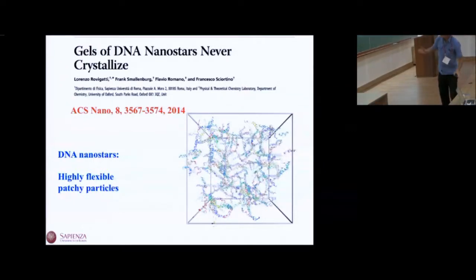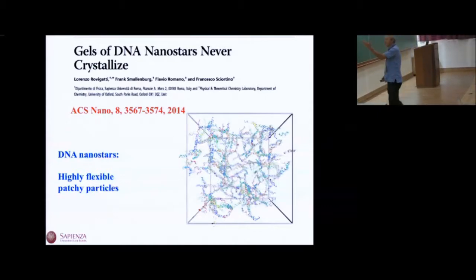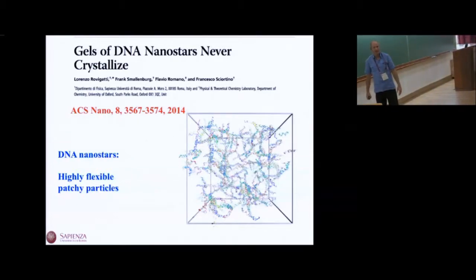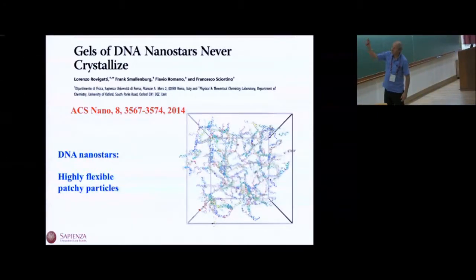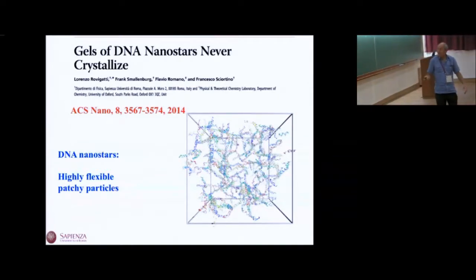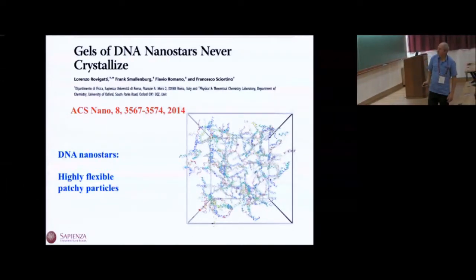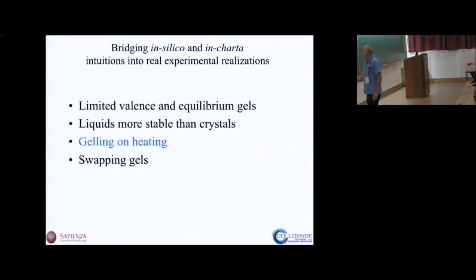It does not crystallize ever. On the computer, you can calculate the free energy with this Frenkel-Ladd type of methods for the DNA gel, or you can do it for the DNA crystal, and you can show that the free energy of this very flexible particles is really lower than the free energy of the crystal. So the gel is the thermodynamically stable state in this kind of system.